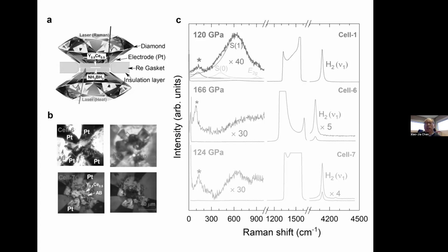Here, we would like to mention the fingerprint we found is a peak at low frequency. You can see here on the right-hand side, around 170 wave number, we mark a star. Actually, that's a fingerprint for hydrides. Also, when you use a laser to hit a sample, you generate hydrogen. In the Raman we can see around 4,000 wave number a clear hydrogen peak. Also, we see some feature from the hydrogen S1, S0 mode here.